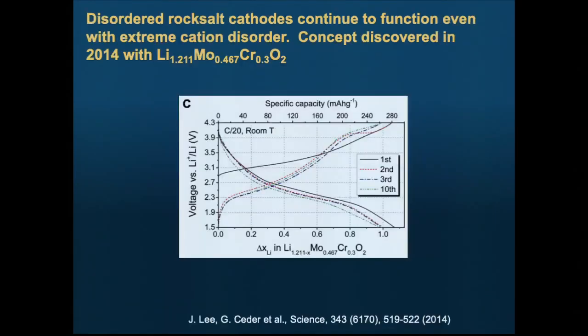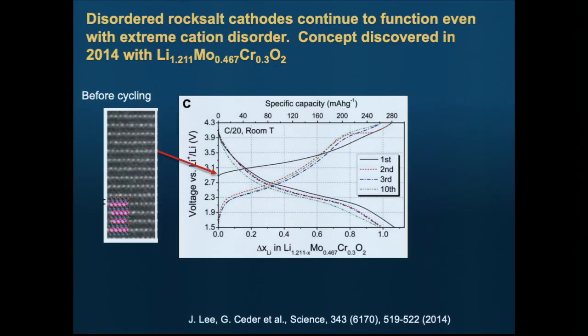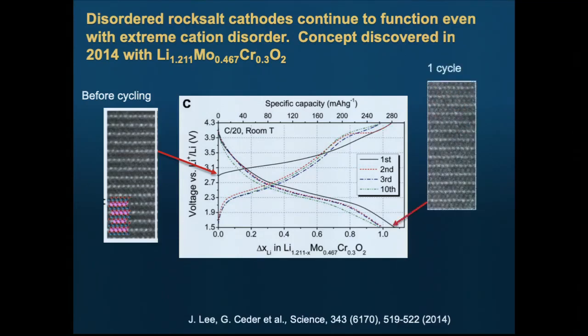So the first material in which we did that was actually a material that started layered. This is a lithium molybdenum chromium oxide. This is a STEM picture. And you actually see the layering, right? Where you don't see anything, that's lithium because it has low Z, right? So this is a well-layered material. This is after one charge discharge cycle. So contrast starts to show up in the lithium layer.